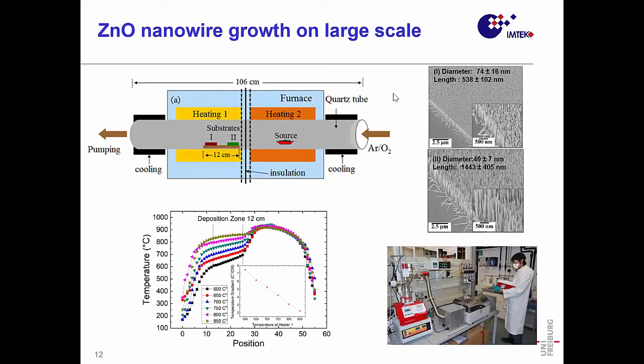Okay, let's now look at temperature. If you want to go to large-scale growth of nanowires over the centimeter range for devices, then you have to control the temperature, and a one-zone oven will not work. You have to have good control. We have now established in my lab a control of growth over 12 centimeters, but still, if you have a gradient of the temperature in this area, then you see that the diameter and the length change, so you need good control of the temperature.